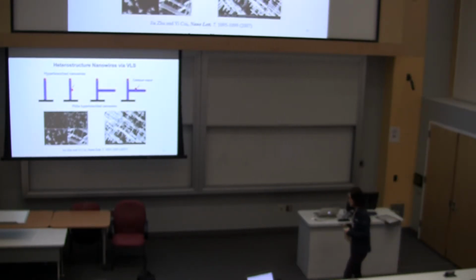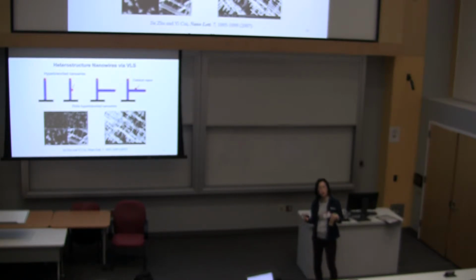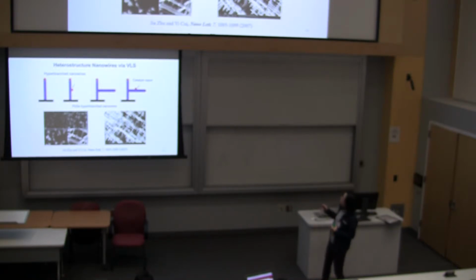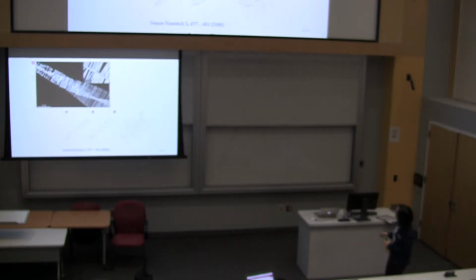I showed you at the beginning lead selenide highly branched nanowire structure, where it was the intrinsic stress points along the central branch that promoted the secondary branch growth. But you can also decorate your central branch with secondary particles and then try to grow the branch. Okay, so at this point we don't really have a control as to exactly where we put the nanowires, but here's a proof of concept that this works. This was an example I showed you before, where here we're not using any secondary metal nanoparticles, but rather the dislocation that's threading across the central branch has periodic stress points that act as nucleation centers.